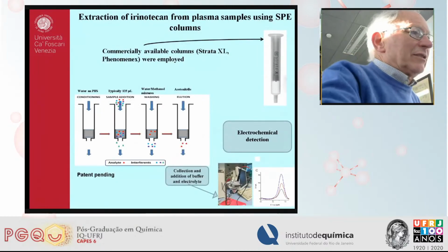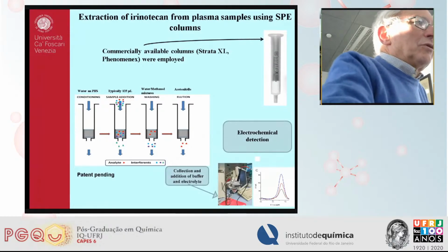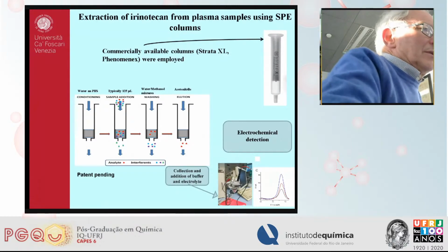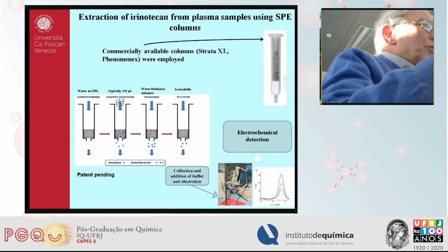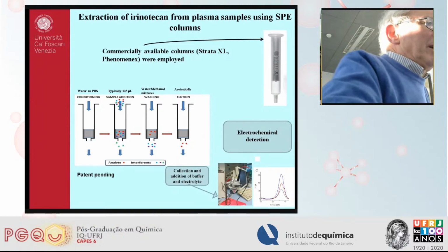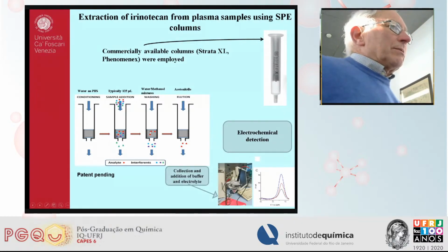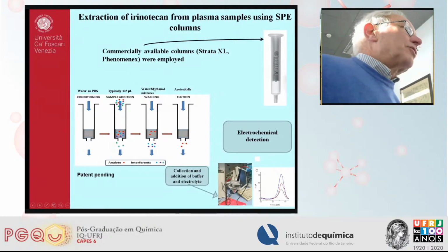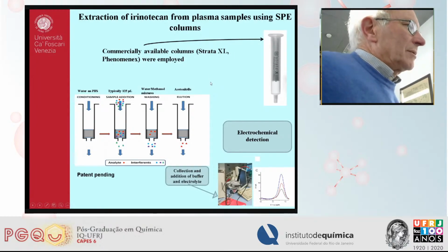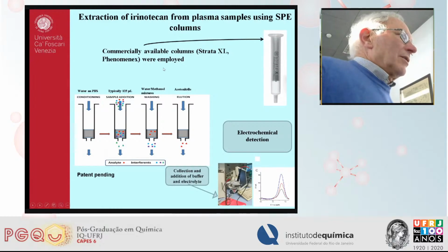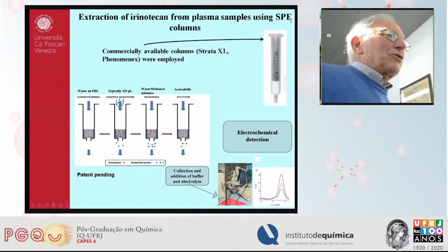So we had to face, as I told you before, the other interferences due to the matrix and also co-therapeutics, which can interfere with the measurement. So in order to get good and reliable results, we have to make an extraction of the drug from plasma samples. To do this, we employed some commercially available solid phase extraction columns, denoted with this acronym, Strata XL, provided by Phenomenex.